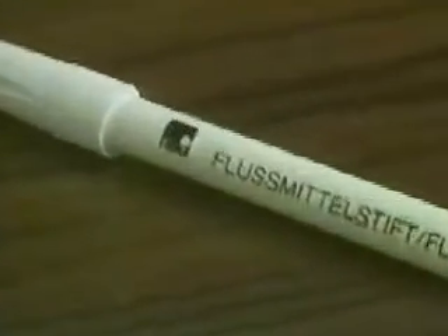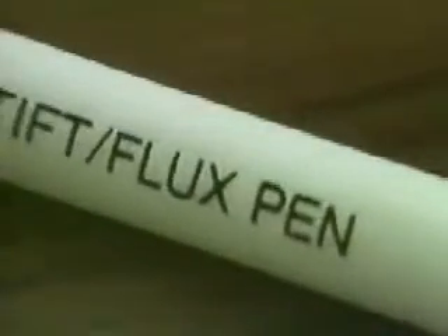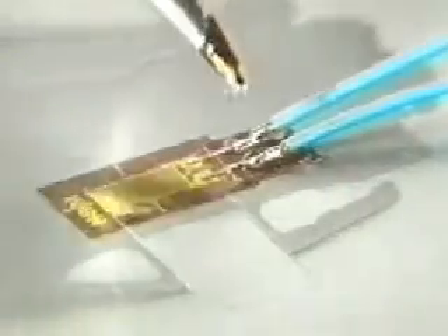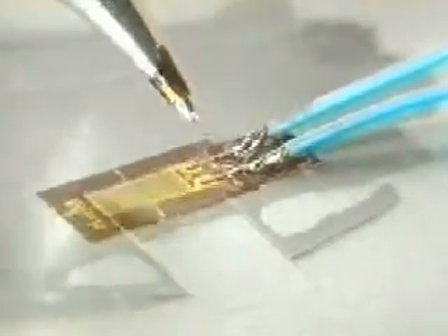The soldering of the cores of the lead to the solder terminals takes place without further addition of solder, simply by melting together the two tinned parts. In order that the solder flows together, the parts must be wetted with flux. If necessary, use a flux dispenser containing colophonium dissolved in methylated spirit. The connections must be held completely steady during soldering. Any movement may give rise to a cold soldered joint.